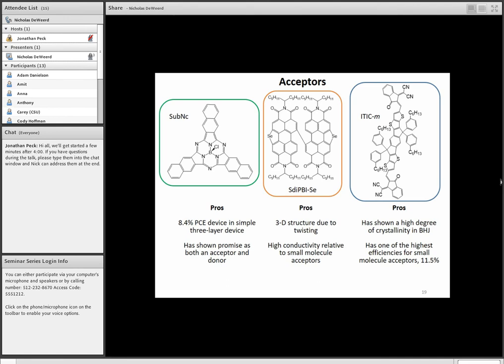And then lastly, we can talk about this high-performing small molecule acceptor. This is ITIC-M, in this case META, and that's just referring to those phenyl rings where they have that C6H13 functional group, a hexyl chain coming off of the META position. So this molecule is really interesting. It's one of the small molecule acceptors that's actually achieved an 11.5% PCE value, so that's really exciting. It looks like the main reason this molecule is performing so well has to do with the degree of crystallinity in the bulk heterojunction. So the more crystalline domains you have, in general, that's going to mean faster charge movement or higher conductivity in the device.